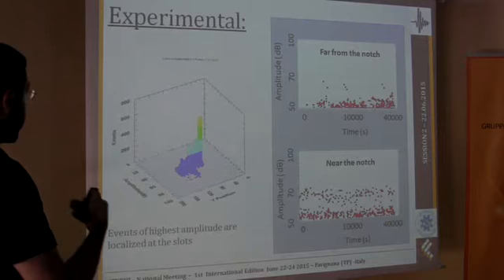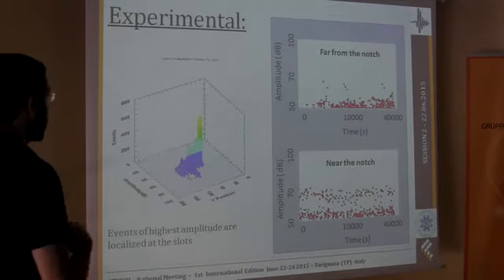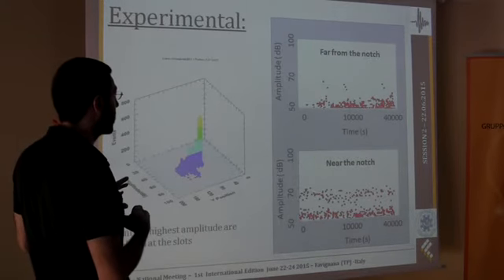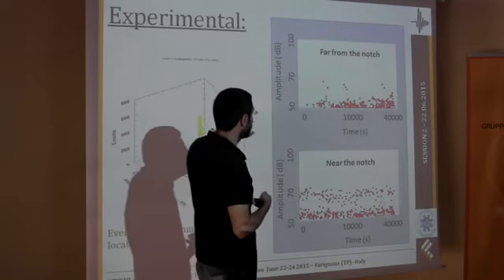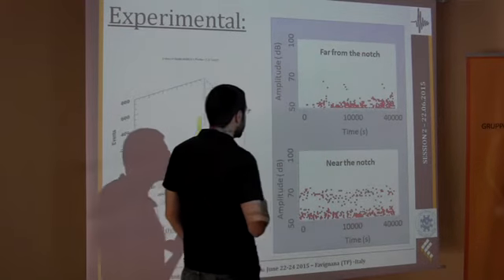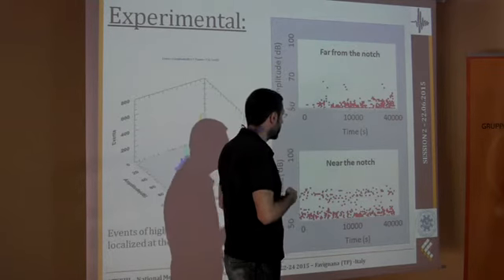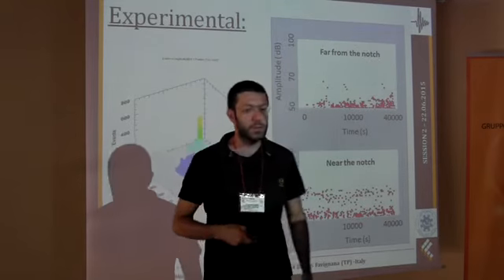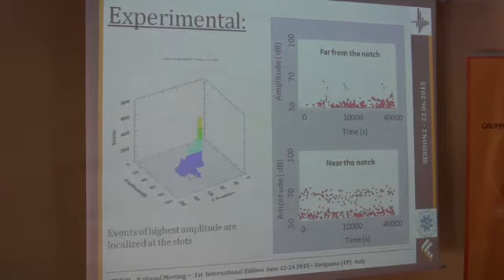So, if we perform an analysis from an amplitude point of view, we also observe that there is a distinction about the amplitude of the events observed near the notch or far from the notch. As you can see, far from the notch, the events have almost this amplitude at about 50 decibels. While if you observe the events which are near the notch, you observe now the occurrence of a second band, that is to say most events near the notch are also events which are higher amplitude.